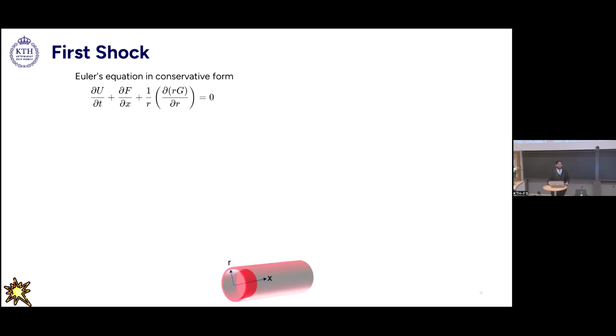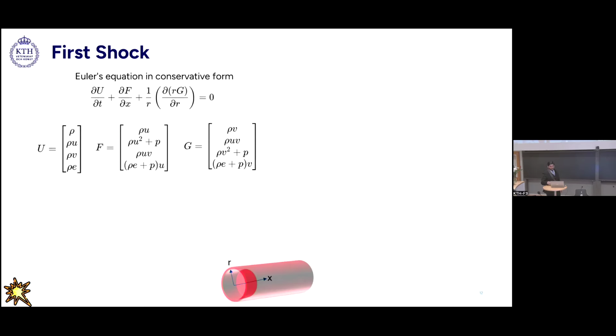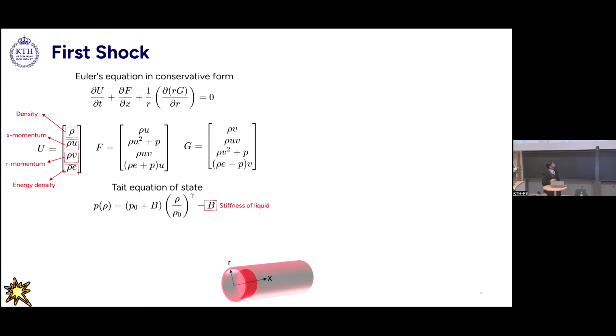Now, we wanted to see how the shock waves are interacting with the material inside. So we wanted to go a little bit into a computational approach. We employed simple Euler's equations in conservative form. We have different variables to be conserved, namely the density, the X momentum equation, the R momentum equation, where X and R are the directions that I have shown here in the experimental chamber, and the energy density. Also, F and G are the fluxes in the X and R directions respectively.